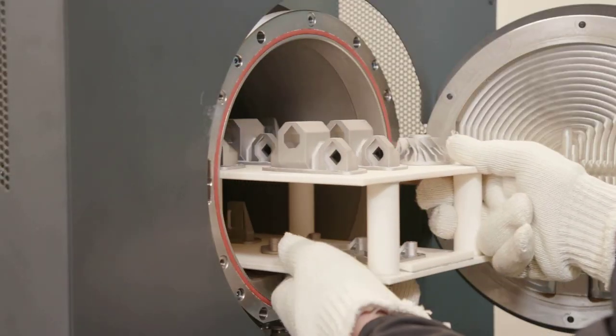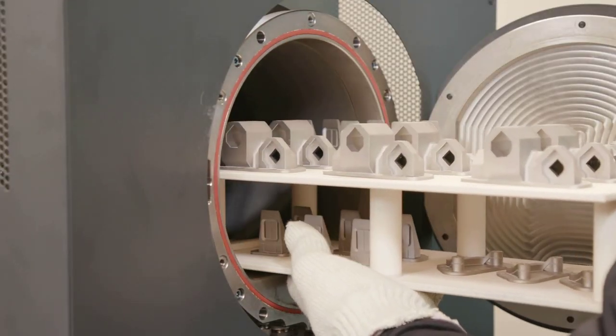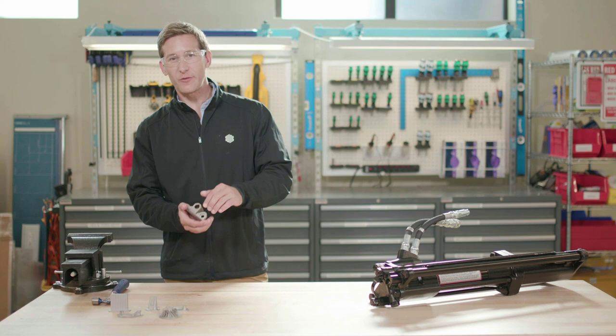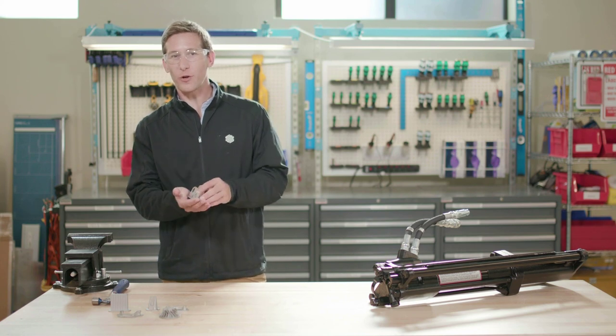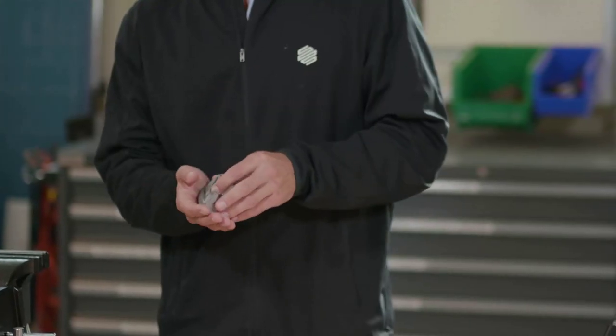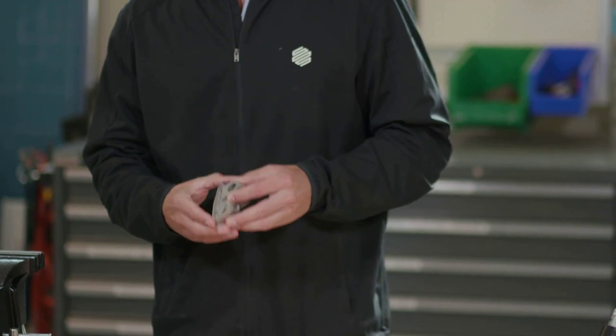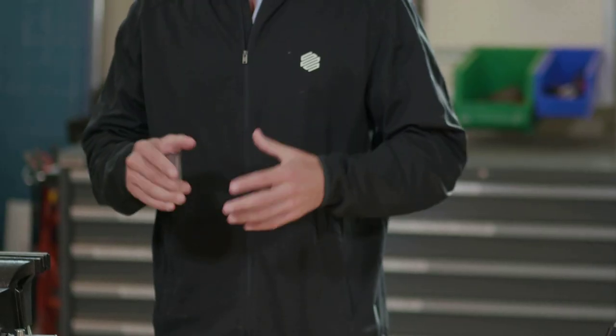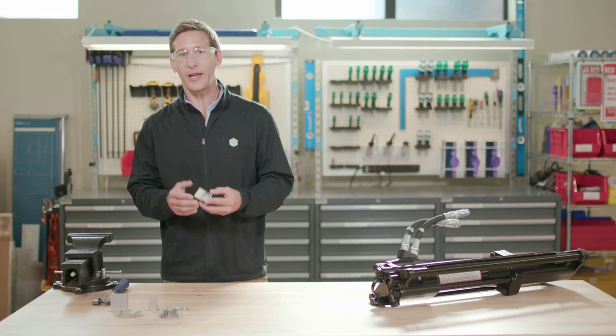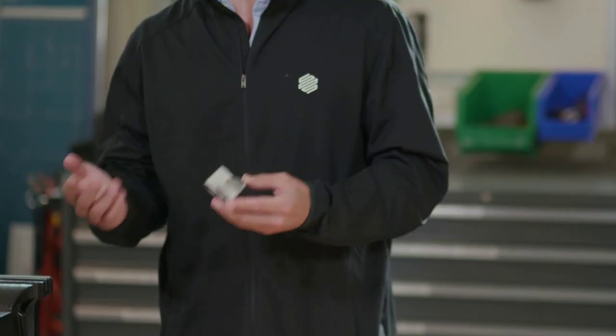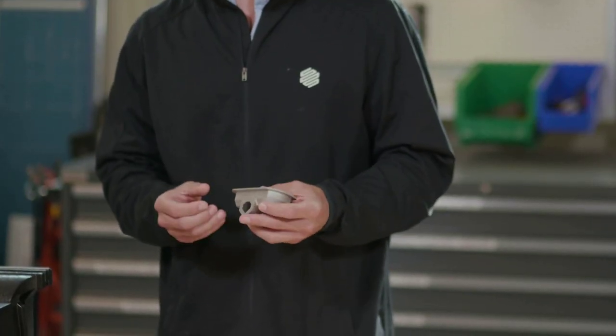Once a run is complete, the setter tray full of finished metal pieces can be removed from the furnace. Once removed from the raft, these parts are ready for use. In the furnace, the layer of printed release material between supports and rafts and your printed part remains powderized. This allows the structure to be tacked to the raft to better control shrink and accuracy throughout the process, but also an easy release after sintering.